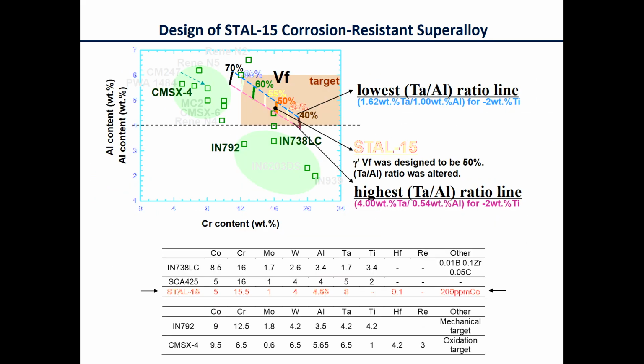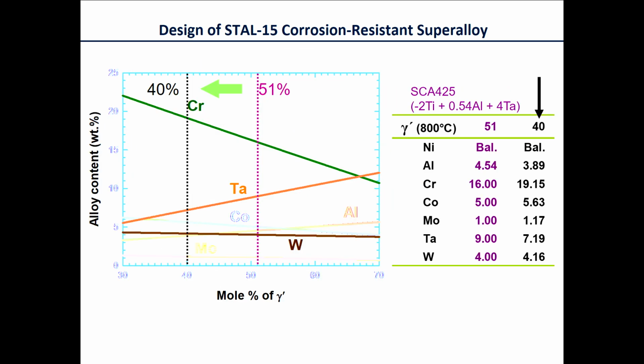Now, this is a composition that we ended up designing here, but the key point of this analysis was to realize that the two phases which are really relevant to these materials, the gamma matrix and the gamma prime precipitating phase, have different propensities for dissolving chromium. So by modifying the amount of the gamma prime forming phase, we were able to push up the net chromium content of the alloy towards higher levels. And in this particular case, it was this concept which is really important.